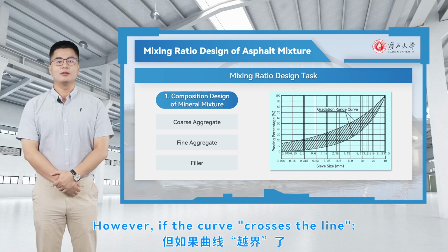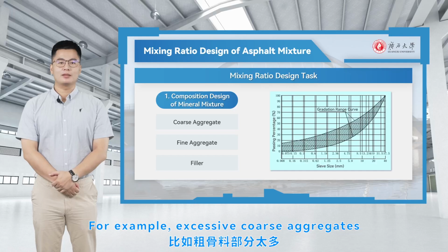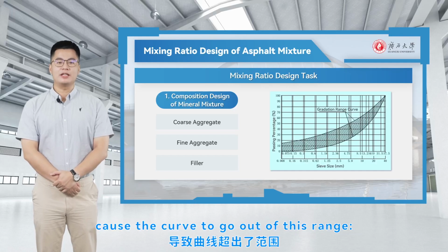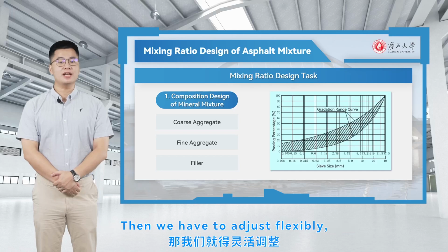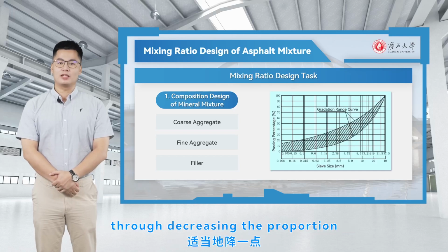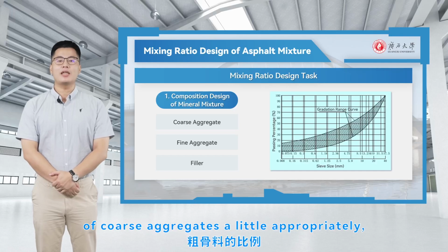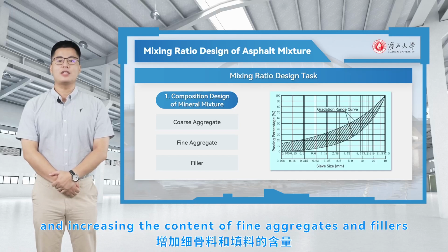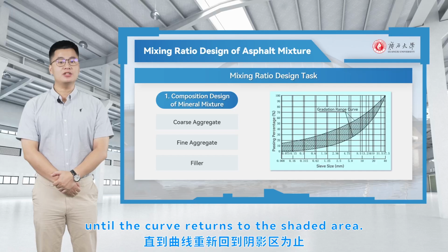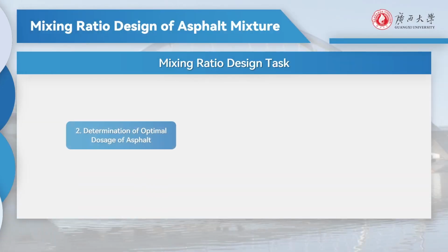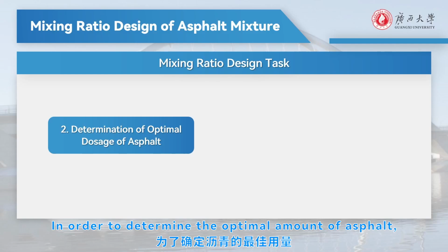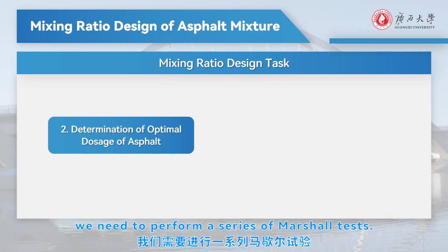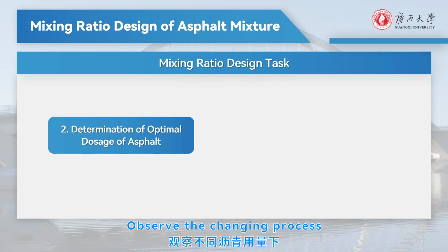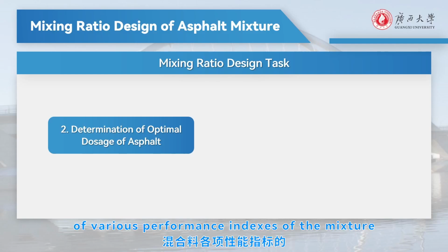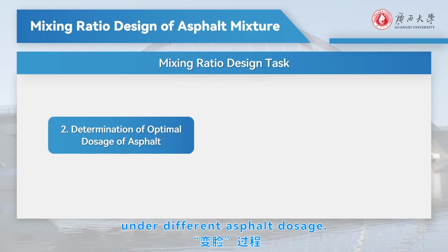However, if the curve crosses the line, for example, excessive coarse aggregates cause the curve to go out of this range, then we have to adjust flexibly through decreasing the proportion of coarse aggregates a little appropriately and increasing the content of fine aggregates and fillers until the curve returns to the shaded area. In order to determine the optimal amount of asphalt, we need to perform a series of Marshall tests. Observe the changing process of various performance indexes of the mixture under different asphalt dosage.